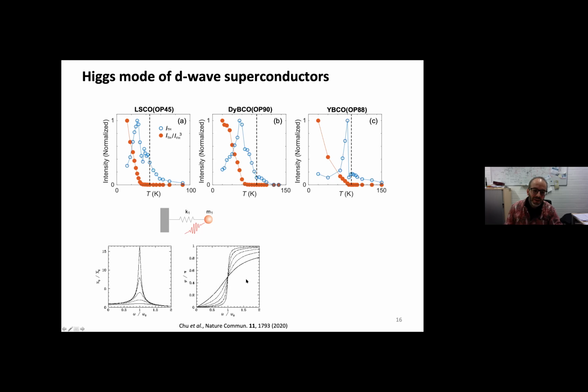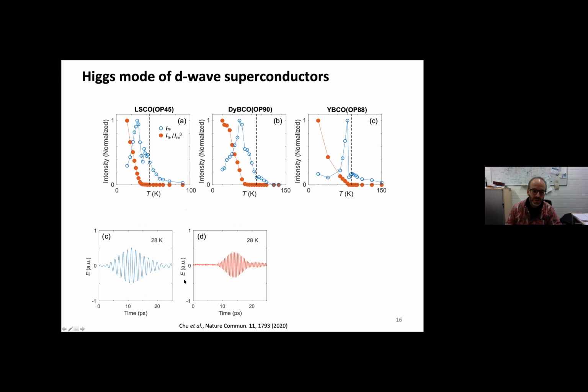And what we are doing now is we want to look at the phase response of this third harmonic generation with respect to our driving field in the system. So we are interested now in the relative phase of this third harmonic generation with respect to this fundamental driving frequency. And the problem in our experiment is it's really difficult for us to tune the frequency of the light continuously in these kinds of experiments. So what we are going to do is, by temperature, we are going to tune the resonance frequency of the gap.